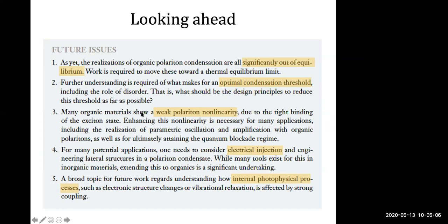In fact, the weak polariton nonlinearity is also limiting in a few different respects. Certainly if you want to reach a strongly correlated regime, or create a polariton blockade, we need to find a way to drastically increase the strength of the polariton nonlinearity, most likely via exciton-exciton interactions, not a simple ground state bleach.